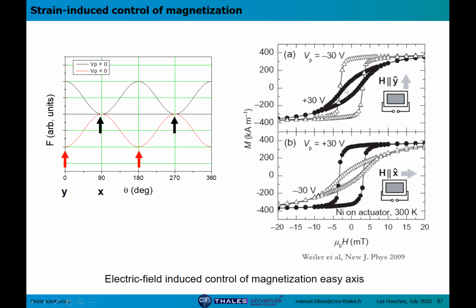So here you can see the magnetization curves measured when the field is applied along Y, vertically here, and here along X. This is for two different electric fields applied. When you have negative voltage, Y is an easy axis and X is a hard axis. And when we have plus 30 volts, X is the easy axis and Y is the hard axis. So you can electrically control the magnetic easy axis.